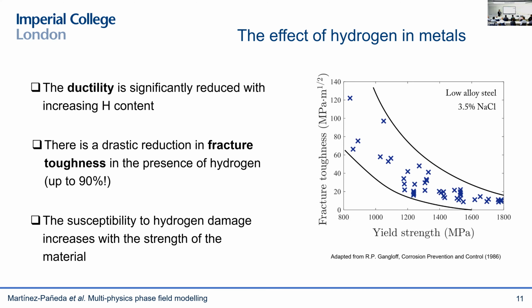And this is a key point to emphasize. The susceptibility to hydrogen damage increases with the material strength. So here you can see fracture toughness for a given hydrogen concentration. So this is typical of exposure to seawater. And you can see that for very high strength steels, the fracture toughness in the presence of hydrogen is below 10 megapascals root meter. So metals become as brittle as ceramics.